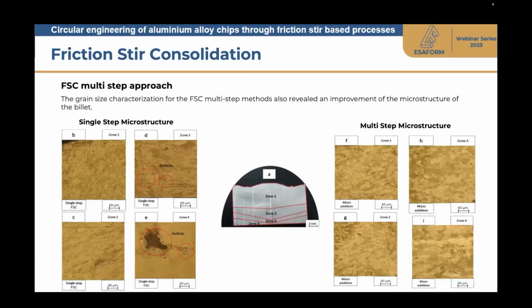And it should be observed that even from optical observations, we can see that several defects characterizing the bottom zones, zone 4 in this image, of the consolidated billet in the single step process are avoided in the multi-step microstructure, in which, in this case, no defects are observed and a more homogeneous material is obtained.